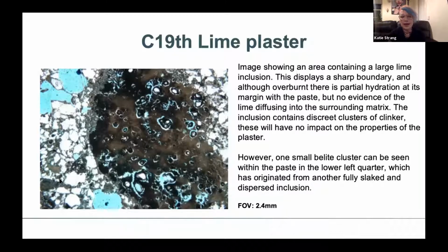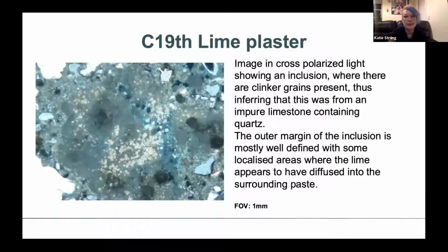So that when that happens, that's when you're imparting strength to your mortar, when you have these silicate minerals throughout the binder. And this is another inclusion here where there's a lot of clinker grains present. Your clinker grains, as I said, are things like your belite, but you also get alite as well and ferrite. So there's different phases. Anyone who's ever looked at Portland cements will know that they're very important components in Portland cement as well, which is why sometimes you need to do quite a lot of analysis to determine the actual composition of a binder, whether it is a cement or a hydraulic lime.